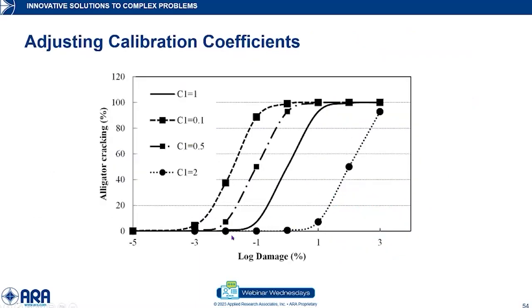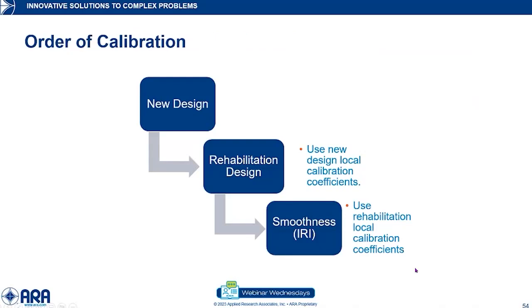And you know, to visually show this a little better what's happening, let's say at 20% alligator cracking. So we said if we increase the C1 coefficient, it's going to decrease the cracking prediction at different damage levels. So at 20% cracking, we have a relatively low, maybe a better way of looking at this is go vertically. So let's say at a given damage level, for the higher coefficient of 2, you can see we have almost no alligator cracking predicted. But then if we go up here to the lower, as we lower the coefficient, then the alligator cracking prediction increases at the same incremental damage level.